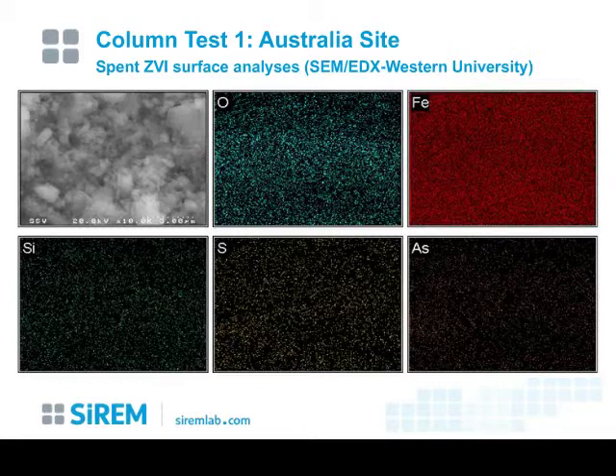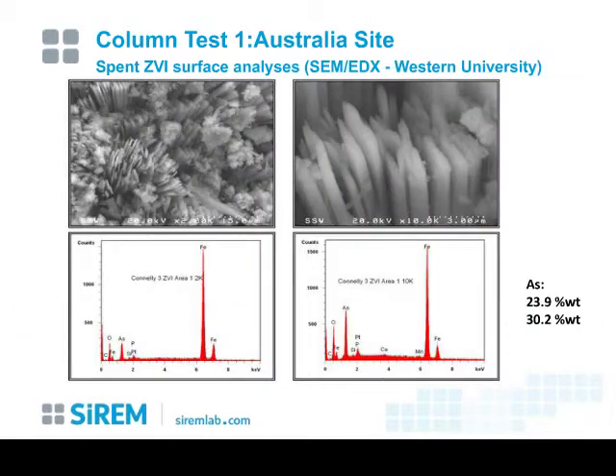I'm not going to go through all these results, but this technology was scanning electron microscopy with an energy dispersive X-ray, and we used this to help understand where the arsenic went and how stable it was. Essentially, it shows that the arsenic absorbed onto iron oxide surfaces, and it was uniformly distributed. I'm not the expert in interpreting these ones. We used a local university, the University of Western Ontario, to help us interpret these results.